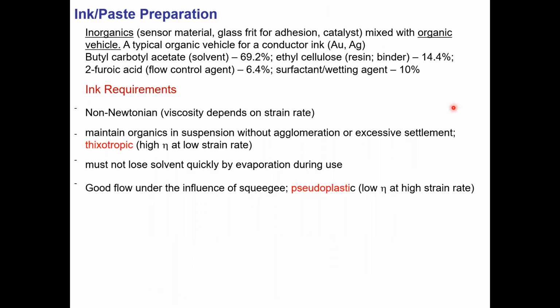So let's talk about how to make this ink that we use for screen printing film. Obviously, you're going to mix your inorganics like sensor material, sometimes added with glass frit for adhesion purposes, or for selective detection, you add catalyst. Mixed with an organic vehicle, a typical organic vehicle is conductor gold or silver with some solvent, and you create the ink. Ink has to be non-Newtonian in terms of the requirement of viscosity. So viscosity will depend on straining rate. For example, it has to be thixotropic